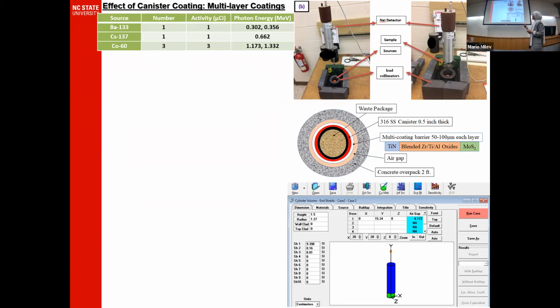The way we perform this experimentally, we have a scintillation detector here, a sodium iodide detector. We place the sample between the detector and the sources. The sources we use are barium-133, cesium-137, and cobalt-60. They have the following photon peak energies, and each one has a certain activity.